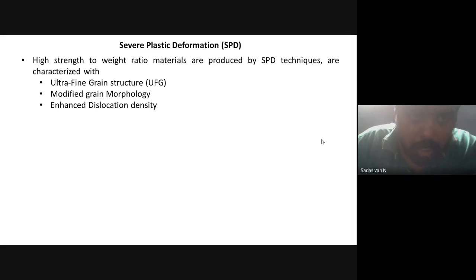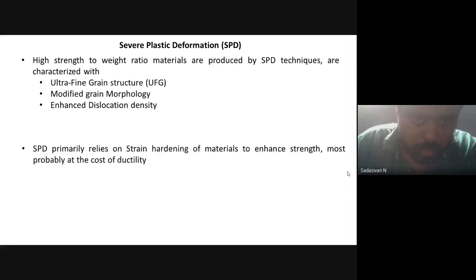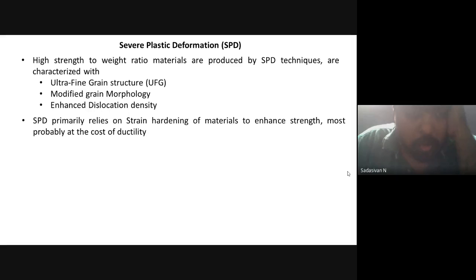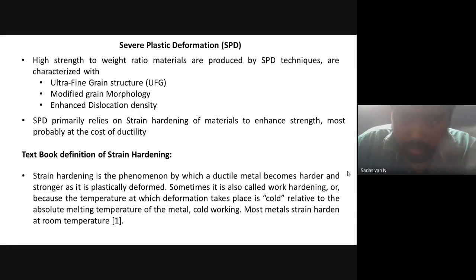So this field, severe plastic deformation, relies on a strengthening mechanism. We strengthen the material by means of strain hardening. So the material that we put through this process comes out with an ultrafine grain structure, and the morphology of the grain totally changes with the enhanced dislocation density. So that is how my material gets normally strengthened. We can go up to even nano range of grain sizes. It relies on strain hardening. So I've given just a definition of what is strain hardening.